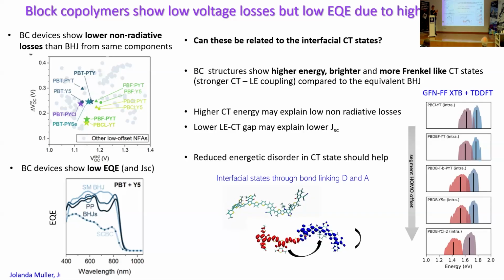the charge transfer-like state is more excitonic than in the case if you had the same materials and they're interacting through space. So it rationalizes why the CT state is more strongly coupled and larger in energy. That rationalizes a larger voltage, and it also rationalizes the idea that there's a smaller driving force for charge separation.